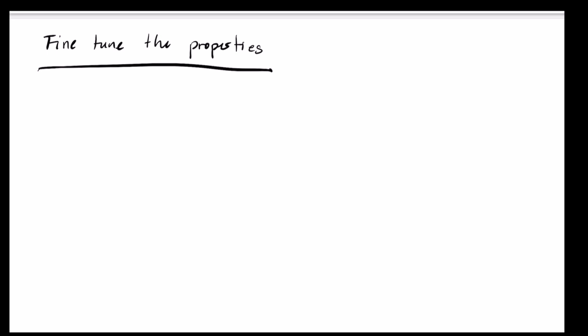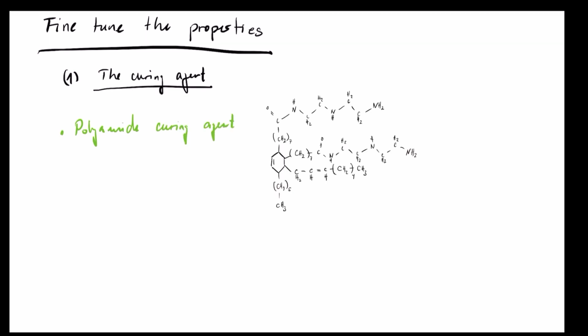And now there's of course a lot of potential to fine-tune the properties of these epoxies. And one way to do it is by using different curing agents. In our example above we had the polyamide curing agent. And as you can see, it is a very large molecule. It has a high molecular mass, and that means that the reaction rate is also slow. In addition to that, we have this fatty acid molecule. And this part here is very hydrophobic, which is why such curing agents are often used for corrosion protection applications.